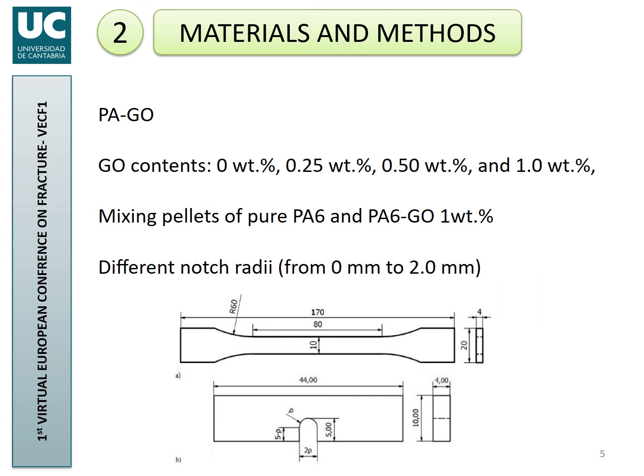So the corresponding mixture of the pellets was performed, and these pellets were introduced in an injection molding machine, and tensile specimens like the one on the top in the figure were injection molded. Just a few of them were used for tensile test, and the other specimens, up to 80 specimens, were cut in the middle section to obtain the fracture specimens like the one shown in the figure on the bottom part. So we are mixing different amounts of graphene oxide in the material, and different notch radius, from 0 up to 2 millimeters.